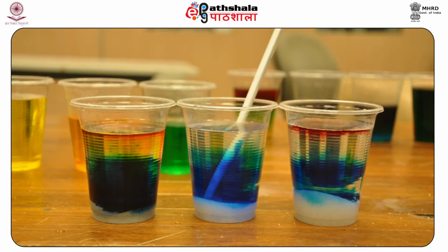In the usual procedure for the development of azoic dyes, the fiber is first impregnated with an alkaline solution of the coupling component. This is then treated with the solution of diazonium compound. The major application of azoic dyes is the dyeing and printing of cellulose fibers like cotton.